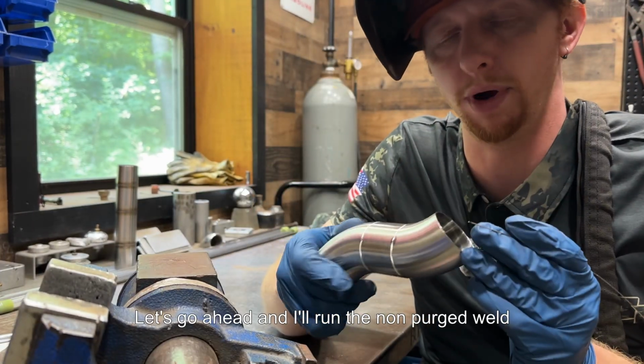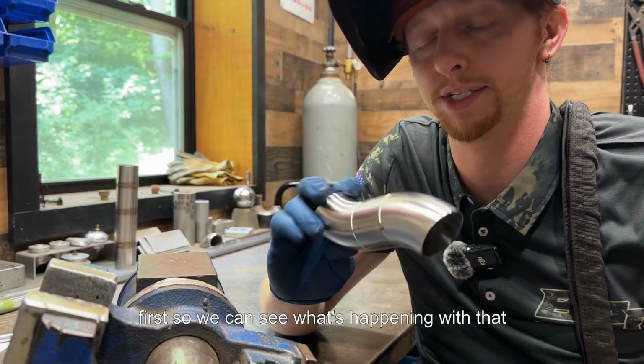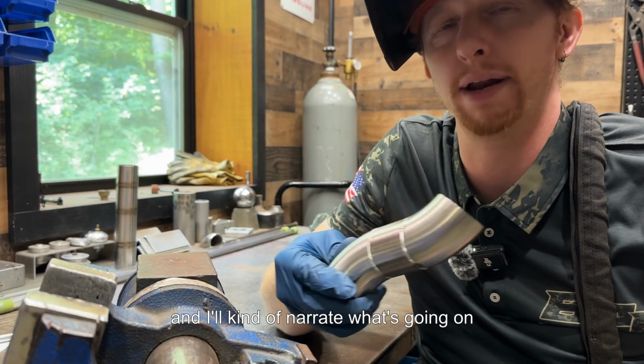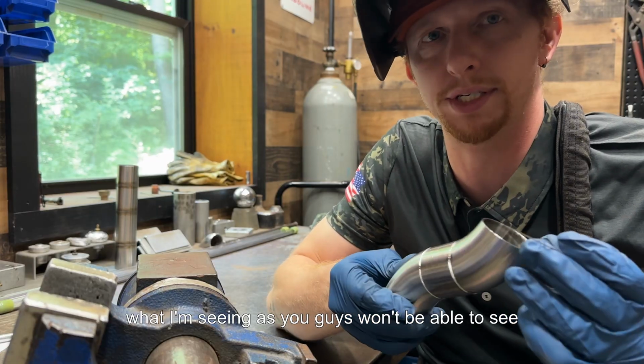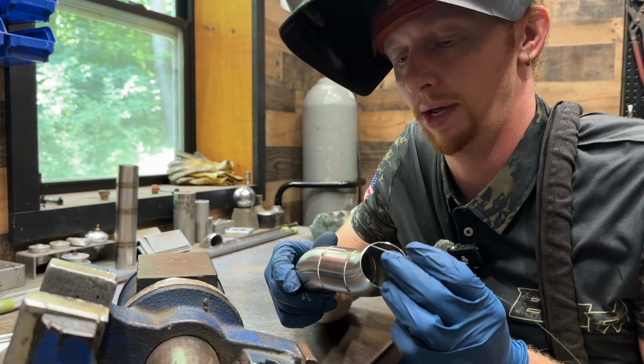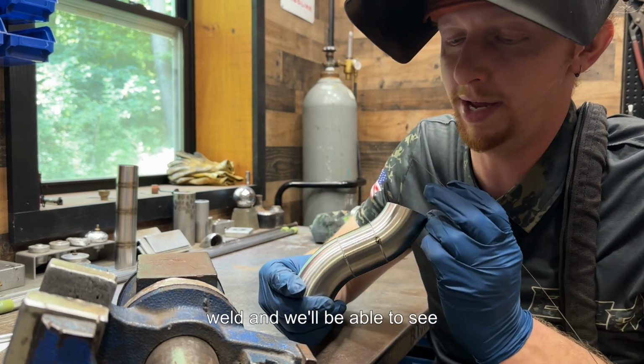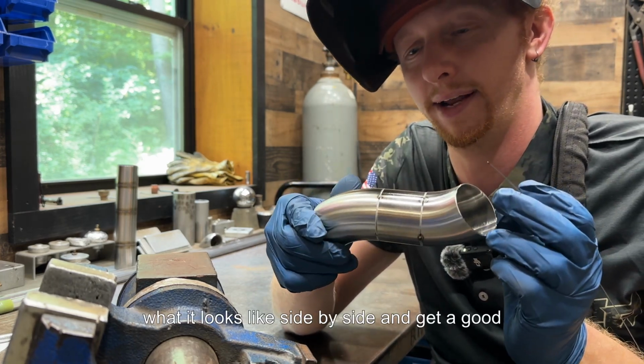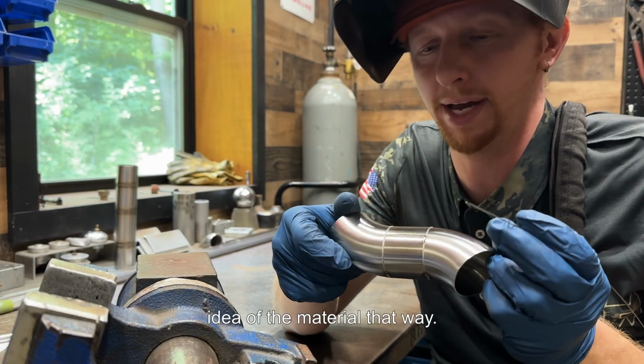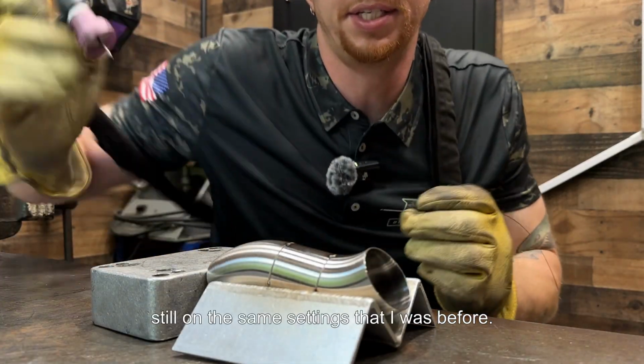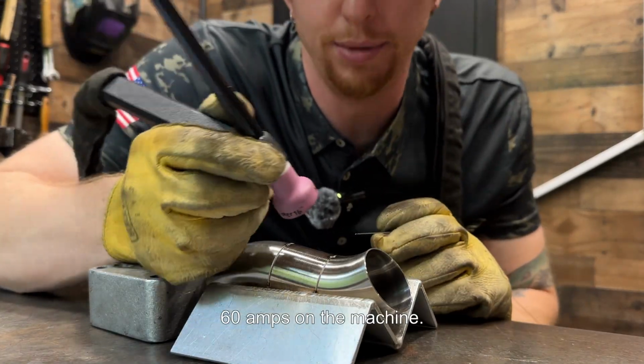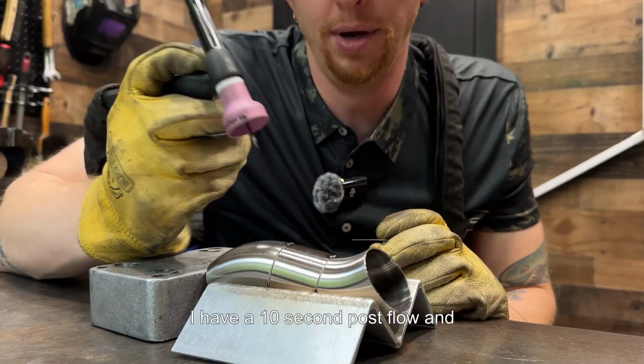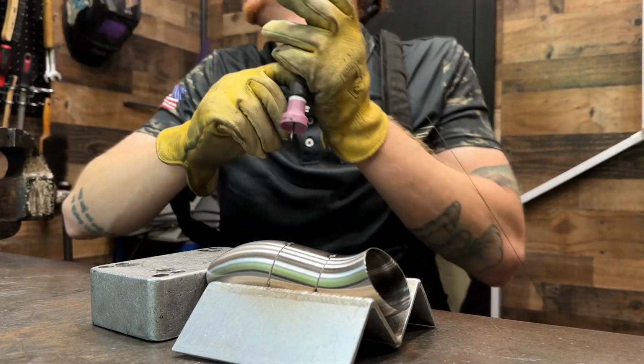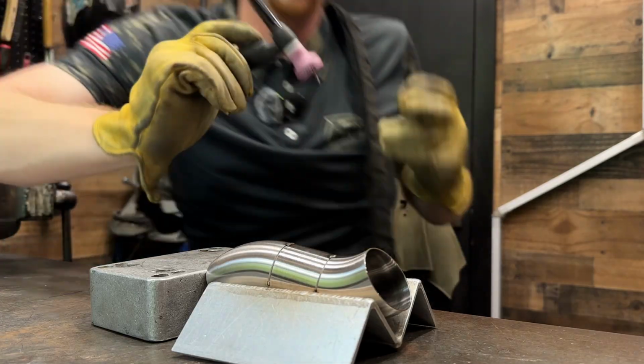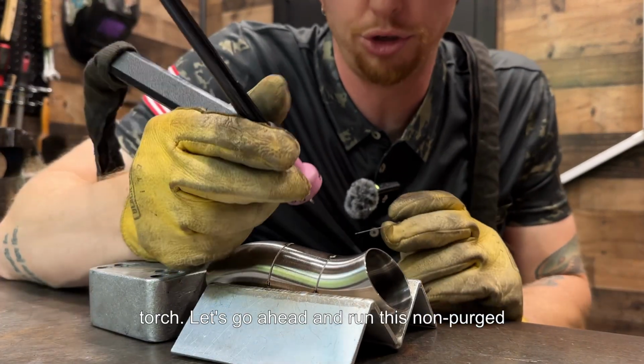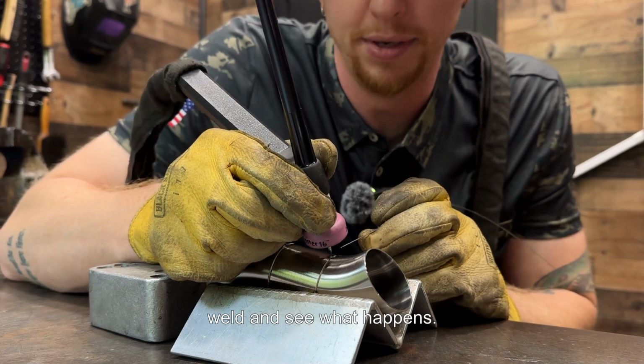So let's go ahead and I'll run the non-purged weld first so we can see what's happening with that, and I'll kind of narrate what's going on, what I'm seeing, as you guys won't be able to see it, unfortunately, since the light is so bright. Then we'll let this cool down and run the purged weld, and we'll be able to see what it looks like side by side and get a good idea of the material that way. Alright, still on the same settings that I was before. Like I said, 60 amps on the machine. I have a 10-second post flow and around 35 cubic feet per hour flowing through the torch. Let's go ahead and run this non-purged weld, see what happens.